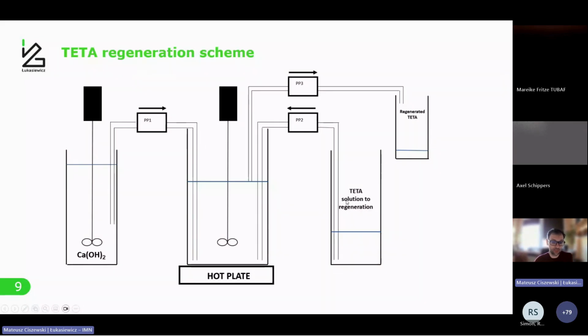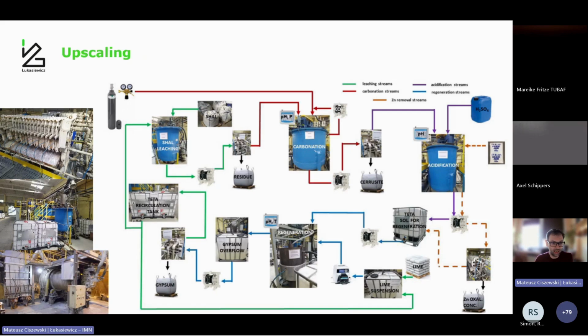This solution, with an increased amount of sulfuric acid, passes to the reactor. From the other side, you have calcium hydroxide delivered by a peristaltic pump, with a proper residence time. The calcium hydroxide is prepared as a suspension, and you have continuous collection of the regenerated TETA solution. So we came up with all these parameters for the process: the time, the temperature, the agitation as well, and it allowed us to pass from lab scale to pilot scale installation.